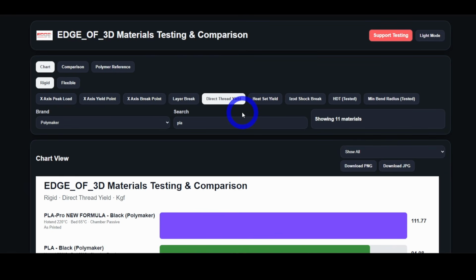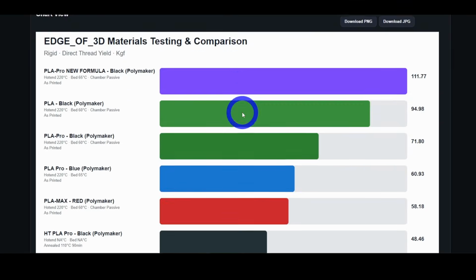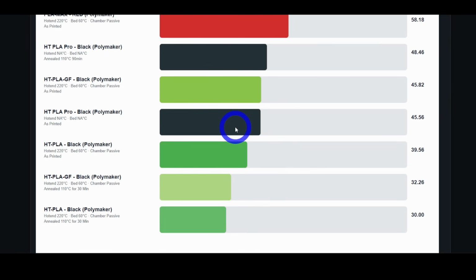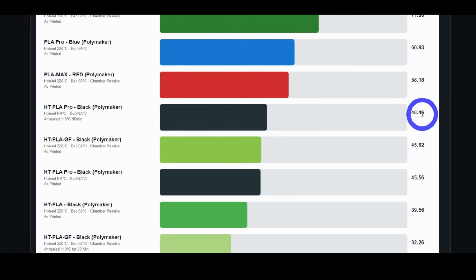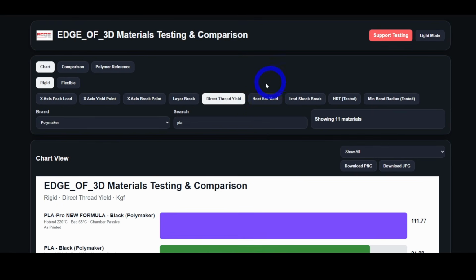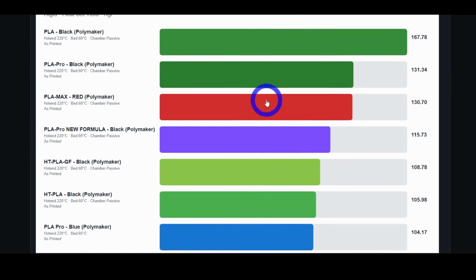Direct thread yield is a 3 millimeter screw screwed into a printed hole 5 millimeters deep and pulled back out. As printed, 45.56 kilograms, and annealed, 48.46. A couple of reasons I do two tests, direct thread and heat set: some materials benefit from heat sets, while other materials don't get a big benefit. What I tell people is, if there's no big benefit from heat sets and you're only going to screw it together once, don't waste your time and money on heat sets. If it's something you're going to continually take apart and put back together, put the heat sets in it.